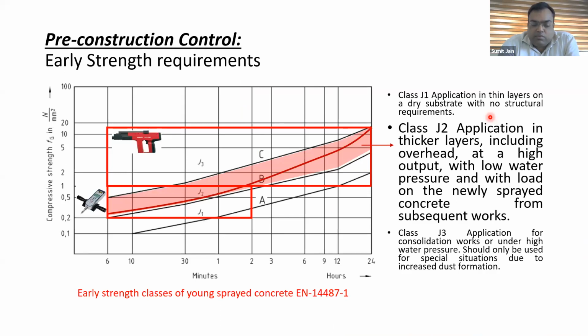This one is the early strength requirement for young age shotcrete, and normally there are 3 classes as per the European norm: class J1, J2, J3. Usually we refer to the J2 class when we are applying in thick layers, including overhead applications, where there is a very high output requirement of the shotcrete, very low water pressure, and load on the newly sprayed concrete from subsequent works. So when we qualify a shotcrete as meeting the J2 class, then all the strength results, as you can see at my pointer, have to fall above this J2 line.